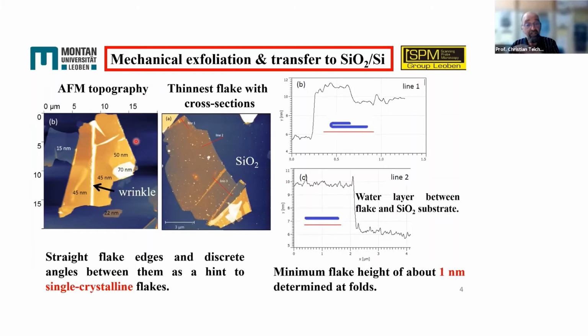So these flakes were exfoliated and transferred to a silicon oxide layer on the silicon wafer. And we have here, as you see, several 10 nanometer thick flakes, but we can thin them down to really 2 nanometer height, as it is shown here in this section line 2. And in line 1, you see a situation where there is a folding, and from that we can assume that the minimum flake height of these flakes is 1 nanometer.